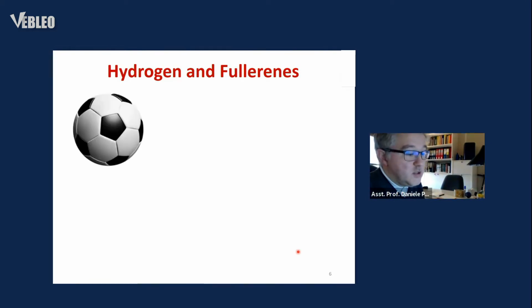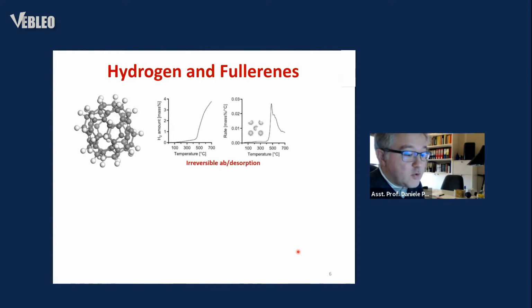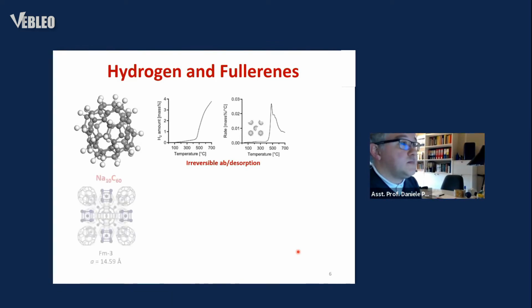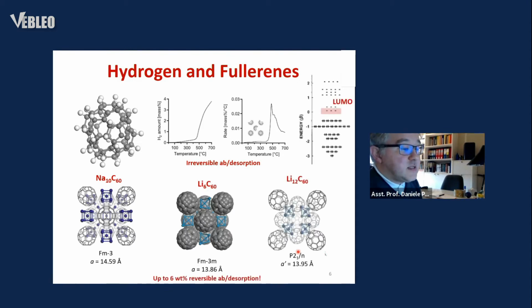If exposed to high temperature and high pressure hydrogen treatment, C60 gets hydrogenated and can covalently absorb a rather large amount of hydrogen. Unfortunately, this process can be reached only at quite extreme conditions, and it is irreversible, as the hydrogen release is followed by fullerene cage collapse. Nevertheless, the chemistry of C60 fullerene is quite rich.